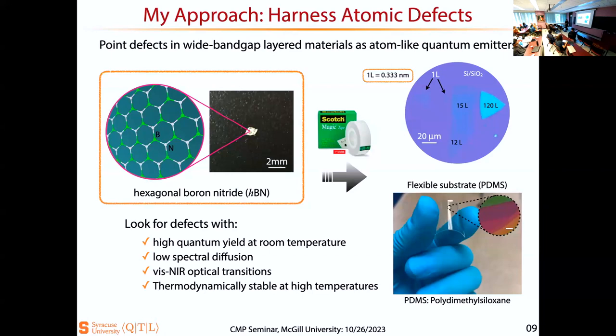Okay, fine. So I would think that with an exfoliated crystal down to 5 layers, you still know that your defect is somewhere in those 5 layers. Absolutely. It's the thickness, but the really good, stable quantum emitters are present when the flake is about 30, 40, 50 nanometers. Yes, that's one of the main reasons. Another question.